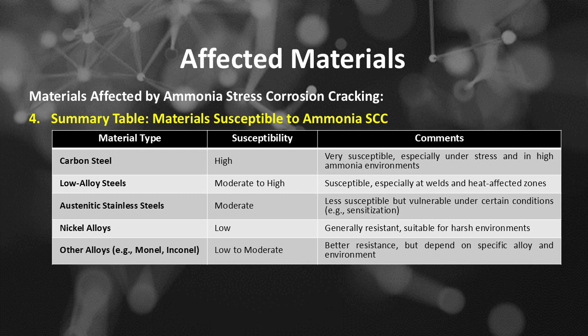Number 3 is austenitic stainless steels. It has moderate susceptibility. Generally better than carbon steel, but not immune. Vulnerable when sensitized, such as by improper heat treatment. Implication, ensure proper fabrication and stress relief practices. Number 4 is nickel alloys. It has low susceptibility. Excellent resistance in harsh environments. Preferred for severe ammonia or corrosive service. Its implication, higher cost, but long-term reliability.